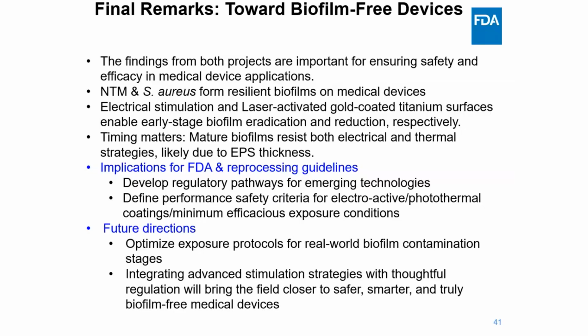And in closing, findings from both projects contribute to a growing understanding of how surface-based strategies may help address persistent biofilm challenges on medical devices. NTM and Staphylococcus biofilms remain difficult to manage, but our results suggest that electrical stimulation and laser-activated gold-coated titanium surfaces may help reduce this biofilm at early stages, emphasizing the value of early intervention. Timing was critical as mature biofilms are significantly harder to treat due to their complex EPS structure.